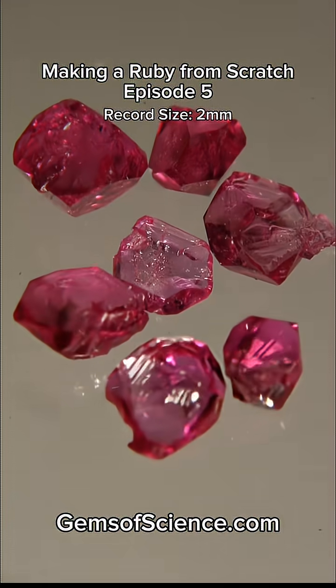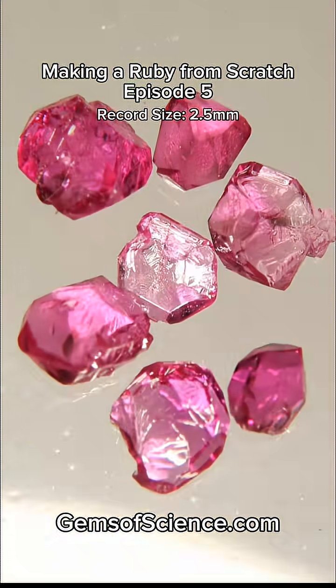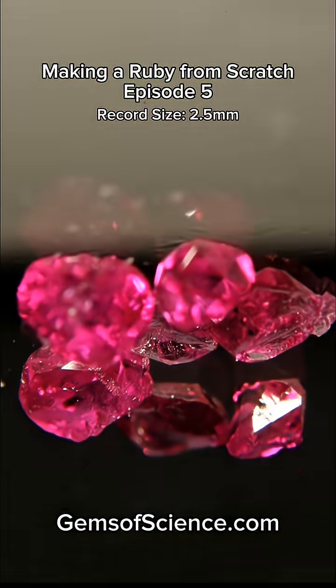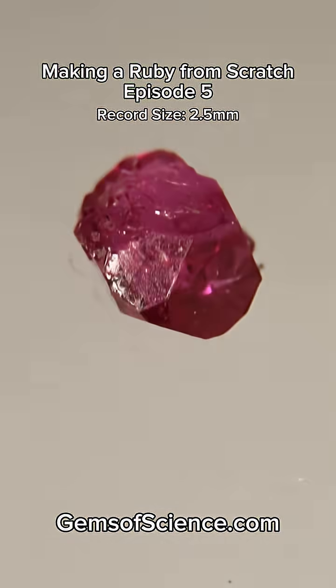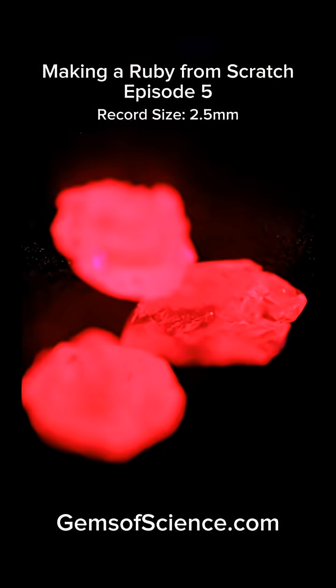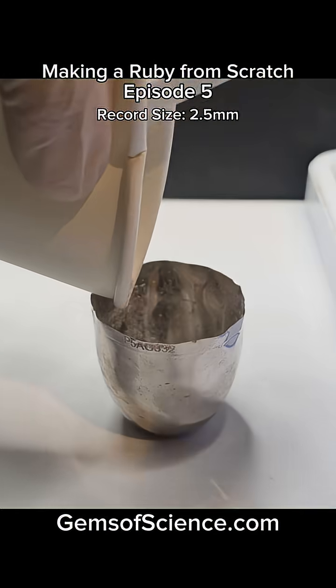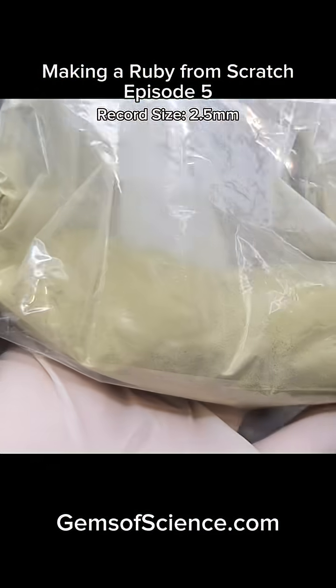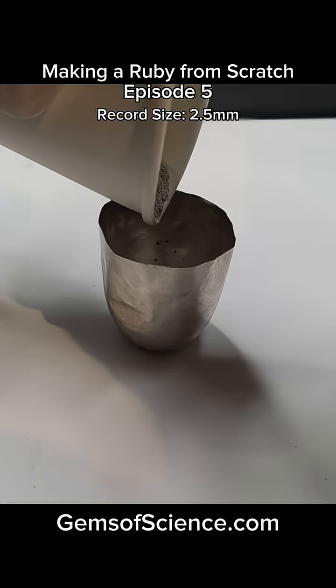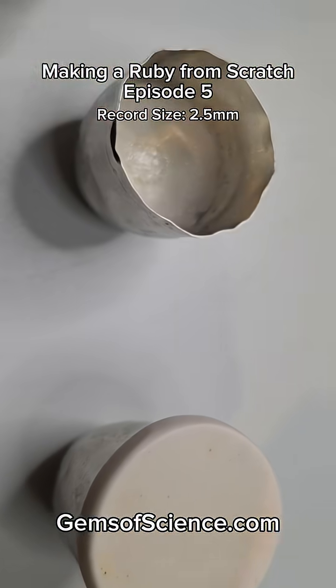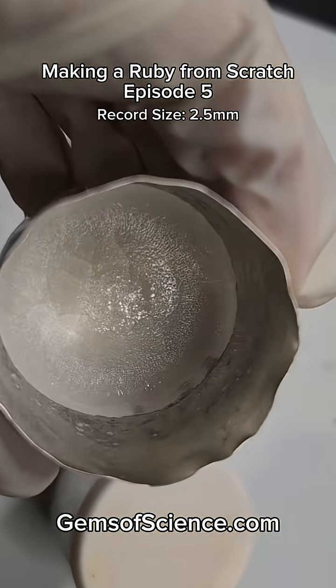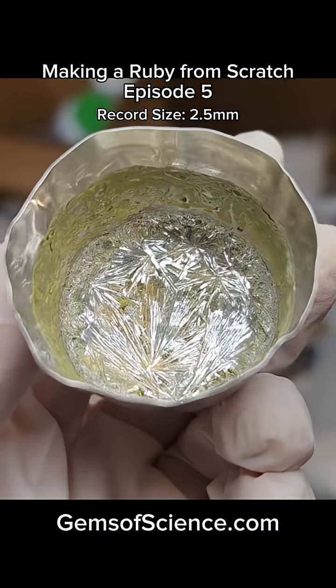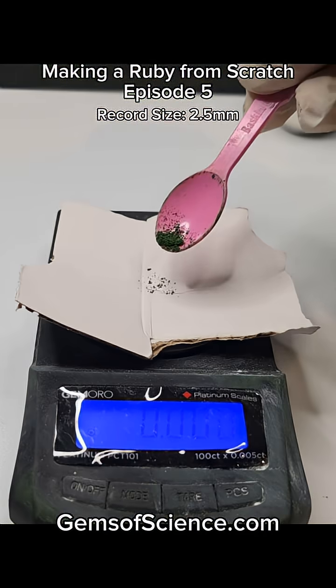Look at these rubies! We're now up to 2.5 millimeters with way more of the bigger ones, all clear with brilliant crystal faces. But we're still a long ways off from the 10 millimeters I'd really like to cut them into gems. And I read about 2 other additives to the flux, sodium and tungsten in one set and lithium carbonate in the other. They didn't give ratios though, so I'm just gonna try a random guess and we'll see what happens. The lithium carbonate mix is kinda boring, but the tungsten flux made its own gorgeous crystals. But we're trying to grow rubies here, so let's get them cooking.